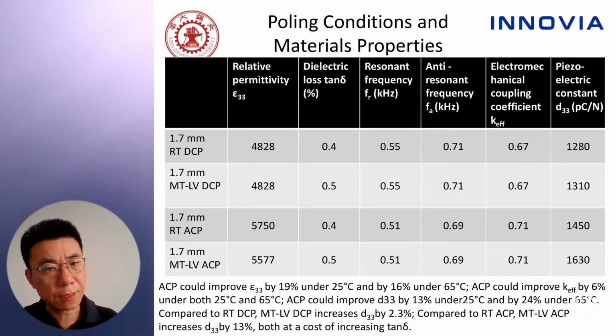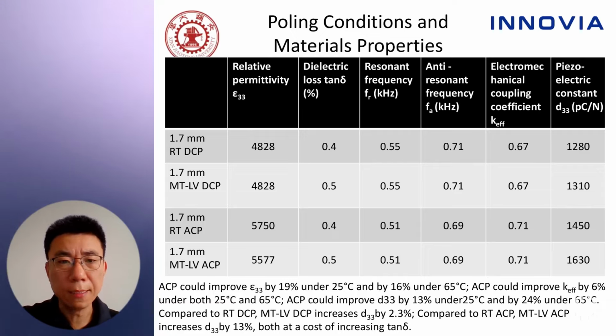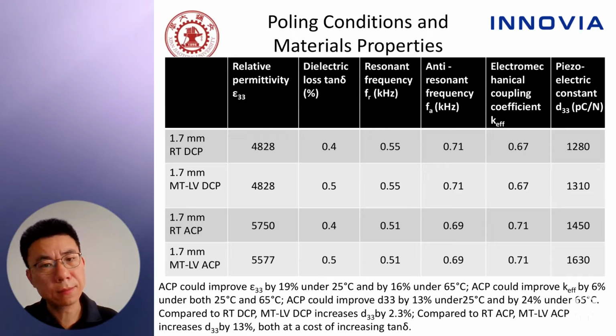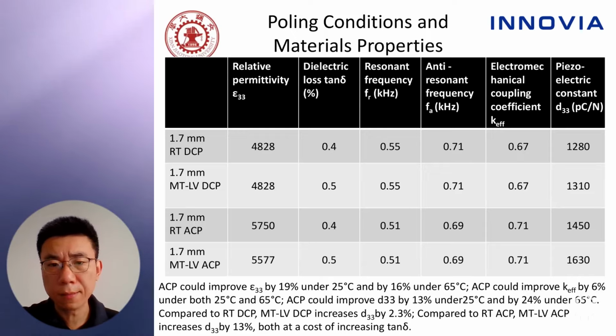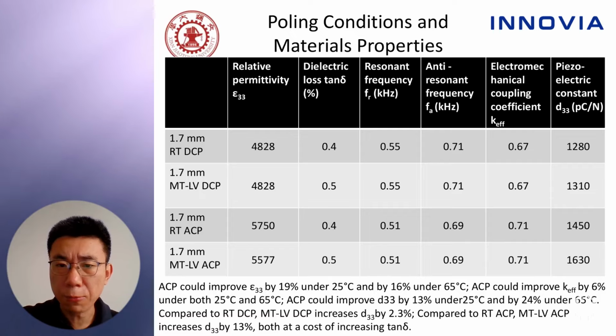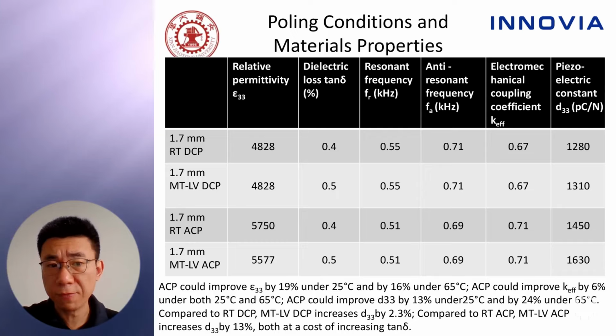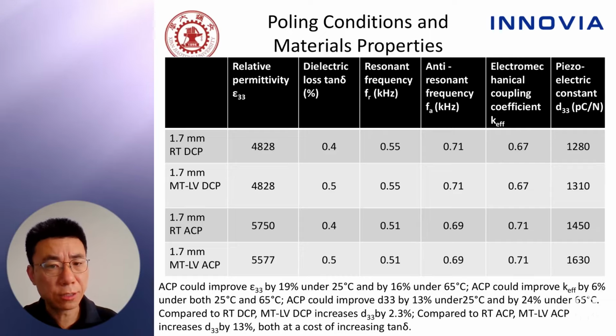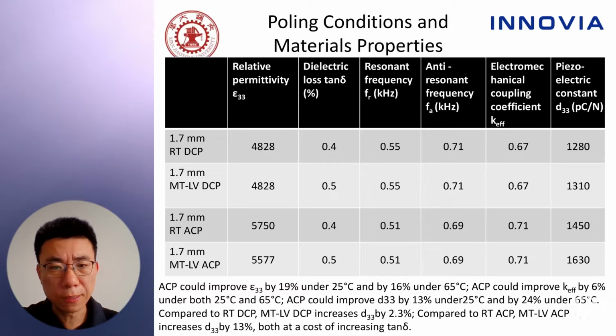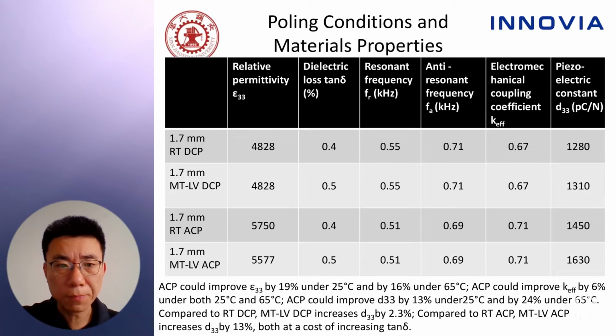Compared to RT-DCP, MT-LV-DCP increases d33 by 2.3%, and with the same comparison, the MT-LV-ACP, or the elevated medium temperature poling with a lower poling voltage, will increase d33 by 13%. Both at the cost of increasing tangent delta or dielectric loss.